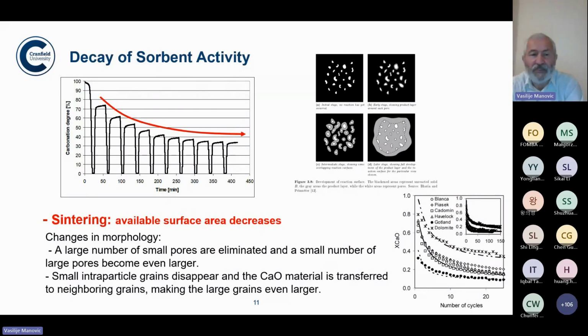In this case, it's just presented simply how the sorbent is losing activity. If it was calcium carbonate at the beginning, you calcine that. This means no CO2 in the material. During the next cycle, it's usually going to about 70% conversion. And with the number of cycles going up, usually we consider some final activity. If you expose material to even 1,000 cycles, there have been publications where researchers were testing material for 1,000 cycles, and usually at the end the activity is 7-8%. So you cannot use material which is only 7-8% active.